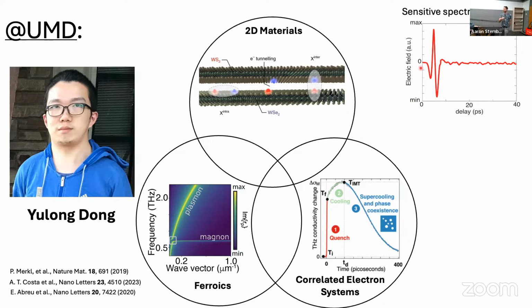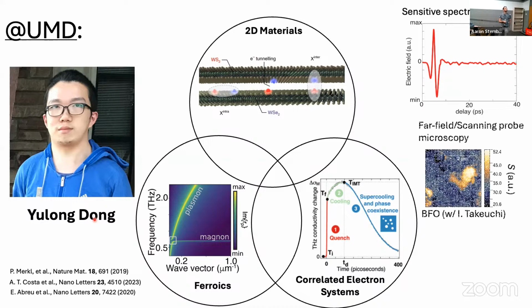And this is data that we've collected in the physical science complex. This is a terahertz beamline that we have that's been developed by Yulong Dong, a student in my group. And we're also developing tools for microscopy so that we can look at how different systems evolve in real space and real time. So this is an image on bismuth ferrite that was provided by Ichiro Takeuchi, showing rather large patches where there's a pretty significant increase in the near field amplitude.